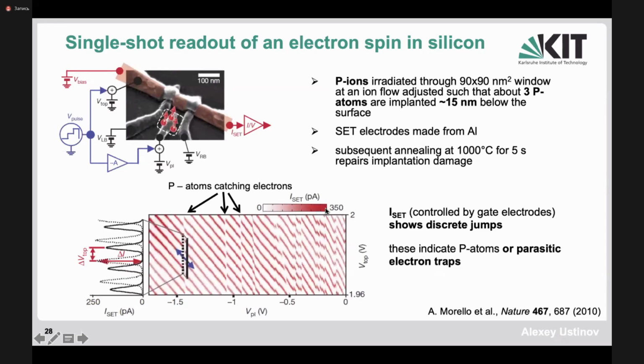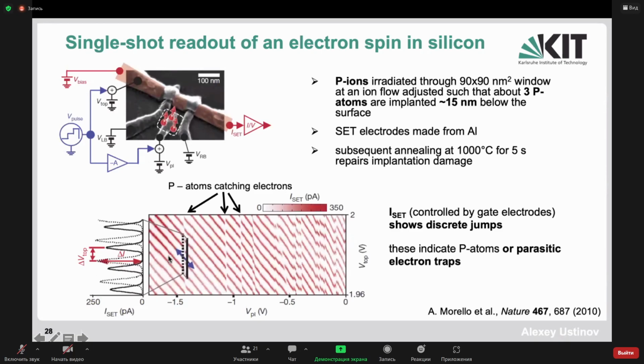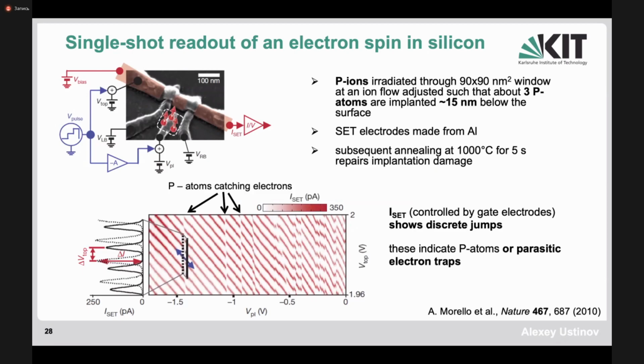You see the current scale is above, so the current was either very small, these are white areas, and red stripes is where the current was arising. And you see these regular stripes basically show us that there are regions of Coulomb blockade separated by lines of current. And if you go from one white stripe across the red stripe to the next white stripe, then the number of electrons on the middle island, on the middle grain, is increasing by 1. So when you overcome the Coulomb blockade, there is a current, and then you go from the state of n electrons, where n, of course, can be very large, to n plus 1 electrons. And this energy which you need to overcome is simply the voltage which you apply multiplied by the electron charge.